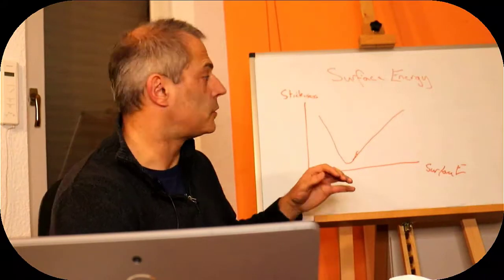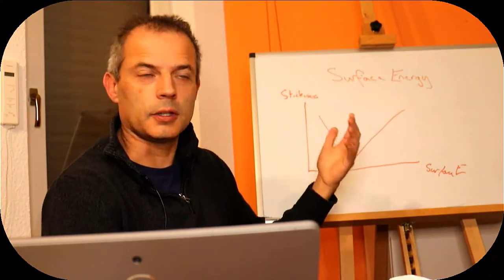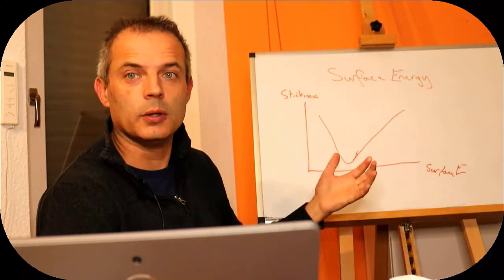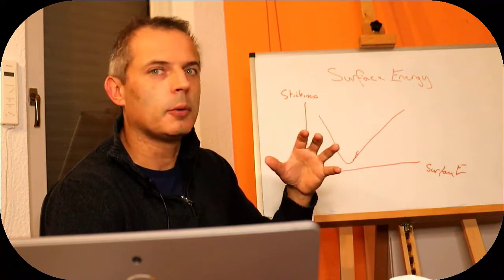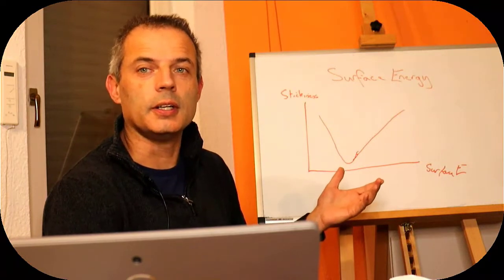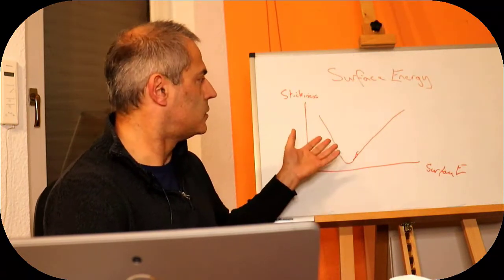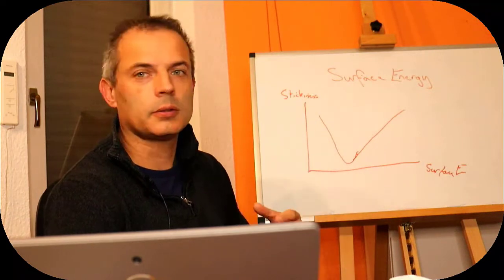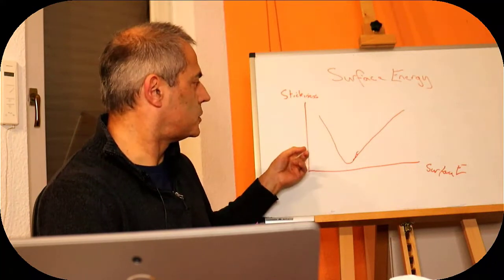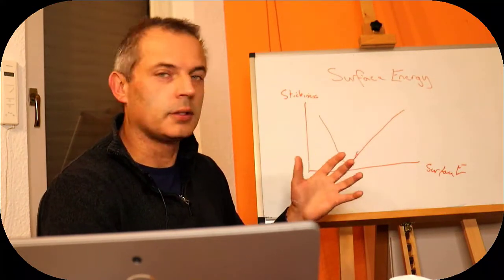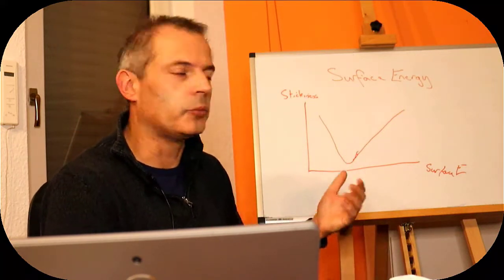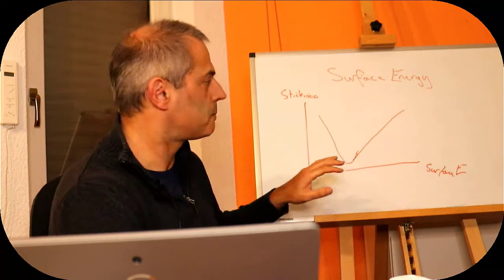So this is the type of curve that we get with low energy. The kind of Teflon repellent surfaces actually cause our protein to stick more with a hydrophobic sticking because water is in there. The water causes it to stick. In fact, in the air it would not stick at all. The interaction is very low, but the water effectively evicts the dissolved protein and pushes it to the surface. We end up with two hydrophobic things sticking together because the water is rejecting them both, and it's lower in energy to have them two together.